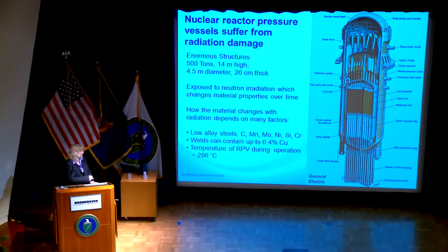So we know that copper causes an increase in the aging rate, and we know that welds have more copper than, say, forgings. So the product form is also important, and also the conditions where the radiation occurs. So under normal operating conditions, the temperature of the reactor pressure vessel is around 290 degrees C. But that temperature can vary slightly, and the variations in the temperature also affect the amount of aging. In addition, there's the amount of energy in the neutrons and the number of neutrons.